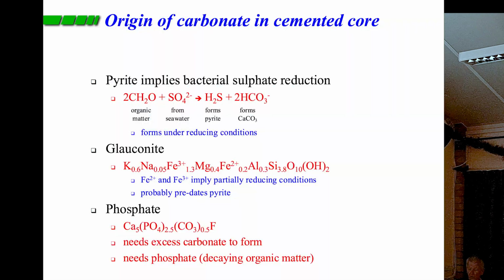Now, what about the cement in the core of the flint? Well, pyrite implies bacterial sulfate reduction, and this H2S, which goes on to form pyrite, but that reaction also releases a lot of bicarbonate, which will act to cement up the core. There's also glauconite present, and this contains iron in the oxidized and reduced state, so it's intermediate level before we reach sulfate reduction.